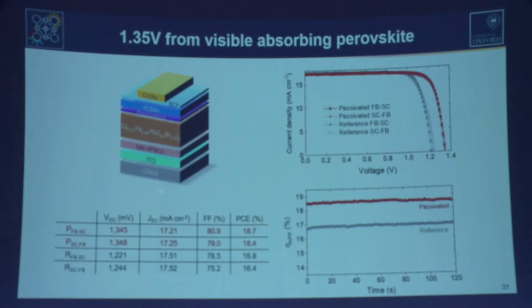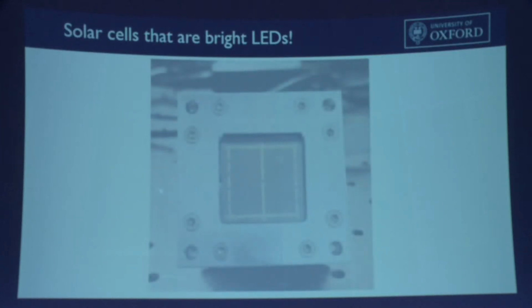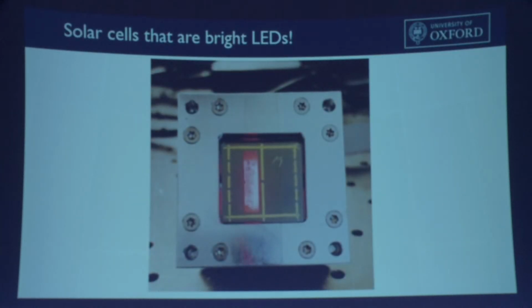We do some treatment on top of the perovskite film as a second step to improve the quality of the interface between the perovskite and the N-type electron transport material. And there, the voltage of these solar cells has now gone up to about 1.35 volts. That's a really big step up in voltage.